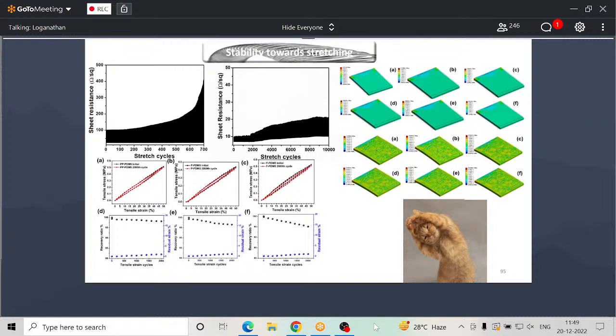We compared the flat PDMS and the pattern PDMS, and they are very stable up to 10,000 stretch cycles. We did this up to 40% strain. And then we also checked the recovery ratio among conventional flat structures and pattern structures. This means that from the FEA analysis, you can see the stress accumulation is better in the pattern structures. So that implies that this kind of structure is good for forming sensors.